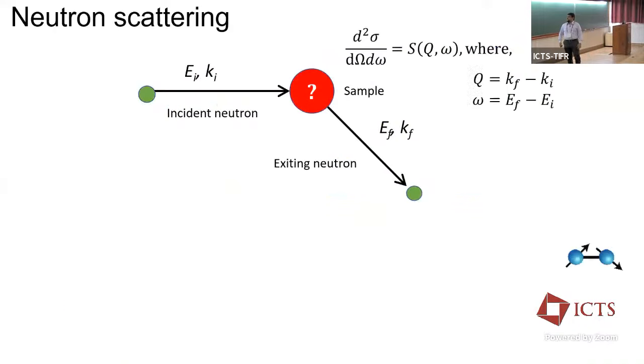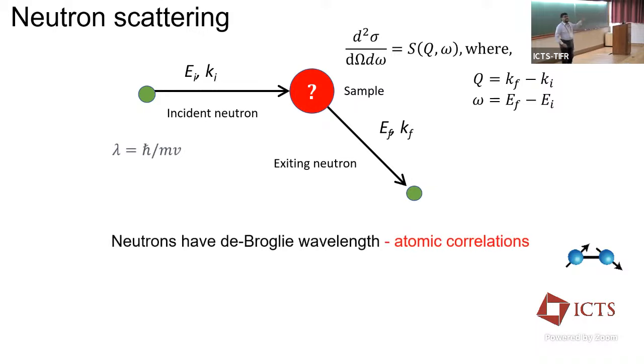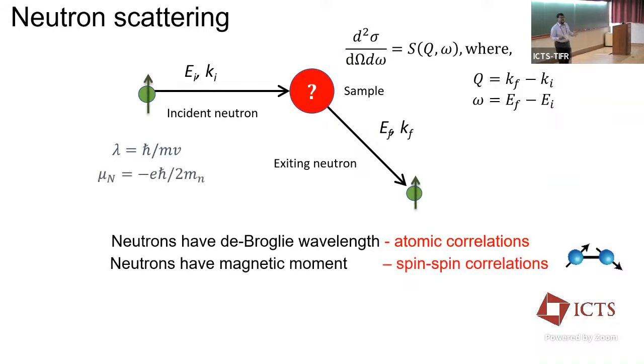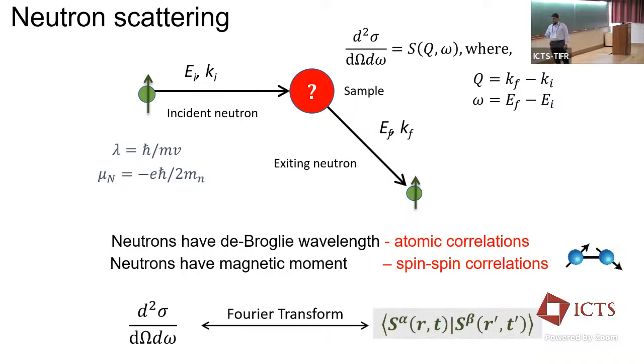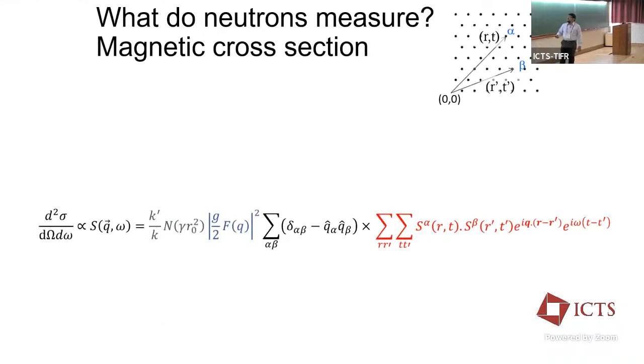So in neutron scattering, neutrons have a mass, so they have a de Broglie wavelength. When it scatters, you get the atomic correlations from that, so you can look at the phonons. However, neutrons also have a magnetic moment. So the spins of the neutrons interact with the spins of the material, so we can also get the spin-spin correlations from there, and the Fourier transform of that is what we really measure. So we get two pieces of information at the same time: the phonons at high Q, and the magnetic information at low Q.